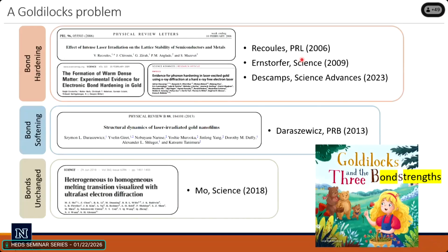It's interesting because even though everything I just explained is generally believed to be true, there is this Goldilocks problem of bond strength, where over the last decade or so, there have been some papers that say bond hardening, some papers that say bond softening, and some papers that say no change whatsoever. The interesting thing about all of these papers, from my point of view, is they actually all have extremely similar experimental results. If you look at their data, it's basically the same in every single one, right? They measure diffraction lines from gold that they pump with a laser, and they all essentially measure the same thing. So why do they all have different results? It's because they all had different guesses for what the ion temperature was, which they're not able to measure. So they all have different models for the ion temperature. They assume different amounts of energy go into the sample. These guys put a factor of half in and just say, oh, half the laser energy goes in compared to these people. I don't know, right? Because everyone's guessing the ion temperature, they're all able to come to different conclusions with essentially the same experimental data set.